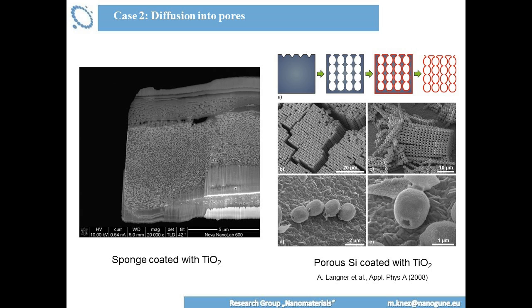Another example is etched silicon wafers. So, undulated etching, it was photoelectrochemically etched and made those nice balls. Then you can do a nice coating with ALD, and then you etch away the substrate, the silicon in this case, and you end up with those very, very nice chains. So it works. This can really work.